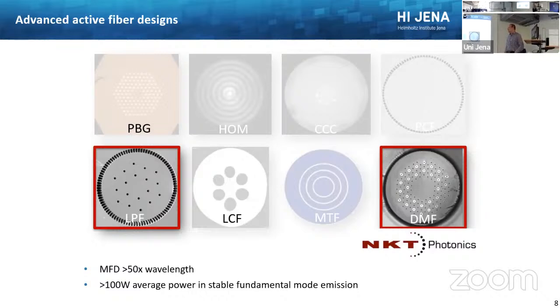The first one is the LPF, large pitch fiber design, because the guiding mechanism, I will talk about it on the next slide, is through these air holes, and the pitch between those air holes is quite large compared to the other fibers. The other one is called DMF rod from NKT Photonics. It's a commercial product, and both can provide, let's say, mode field diameters of over 50 times the wavelength. So at 1 micron, over 50 microns, and you can get stable single mode operation up to a bit more than 100 watts.